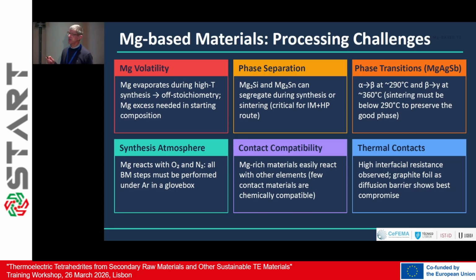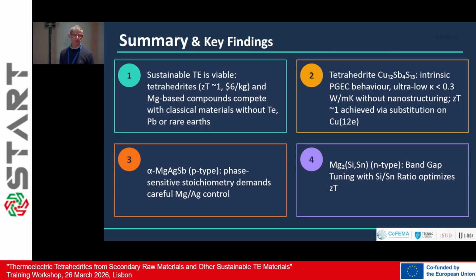And because of its reactivity, it's not easy to find the proper contact or diffusion barriers with this kind of materials. And not only the electrical conducting contacts, but also the thermal contacts. So there are still some challenges, in particular for developing devices that will survive for long periods. So finally, we think that sustainable thermoelectrics is viable.